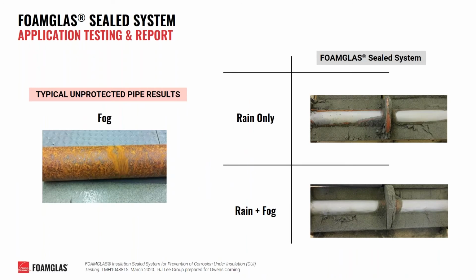Here on the left, you can see an example of what a typical unprotected pipe will look like upon conclusion of this 28-day test. You can see, just based on the surface alone, very obvious signs of heavy corrosion taking place. Where on the right, you can see the 28-day results of the FOAMGLAS Sealed System for both rain only and rain plus fog. Note that the faint orange color that you may be seeing in the middle of that system is actually from the sealant during the installation of the system and not indicative of corrosion taking place.